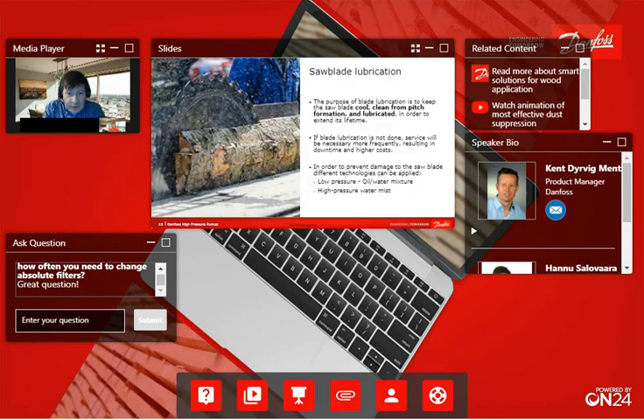We can jump to the next. Then we are jumping into saw blade lubrication. The very fine water mist is excellent for saw blade lubrication, because with this water mist we can keep the saw blade cool, clean from the resin, and also lubricate it, so it gives a much better lifetime for the saw blade, and also helps to keep the saw blade sharp.